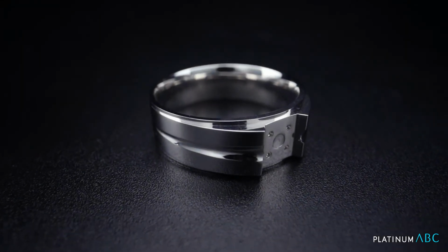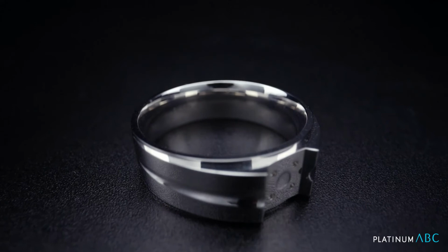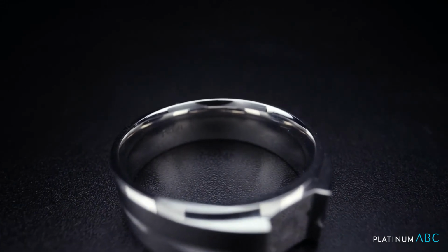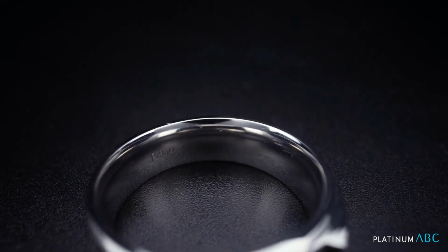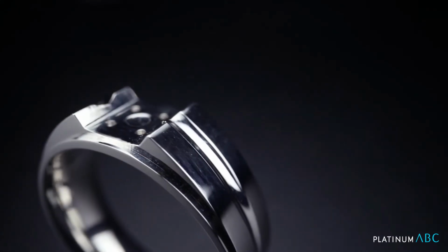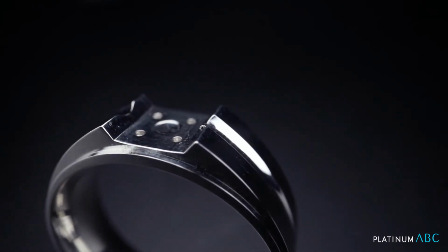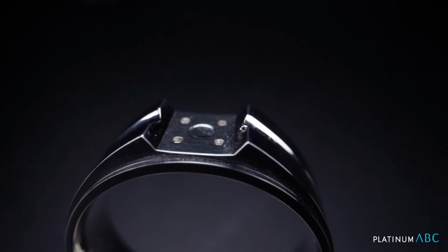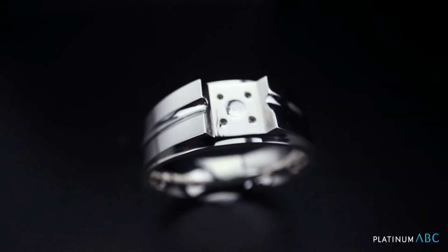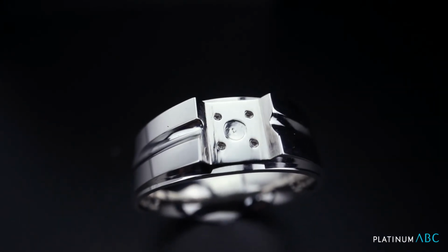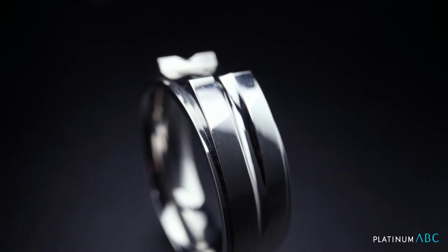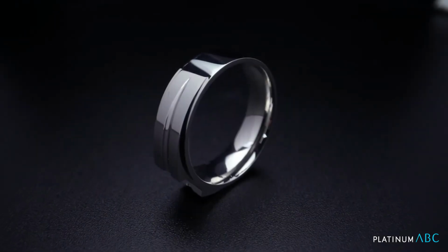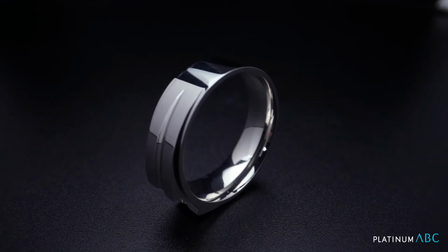Here we see platinum ruthenium gallium samples that were CNC'd after casting. Normally, one would expect a huge amount of shrinkage porosity when CNC cuts into the subsurface of the platinum Ru alloy. In our testing, however, the CNC samples came out very clean. There's no sign of serious porosity in the subsurface area of the cast.